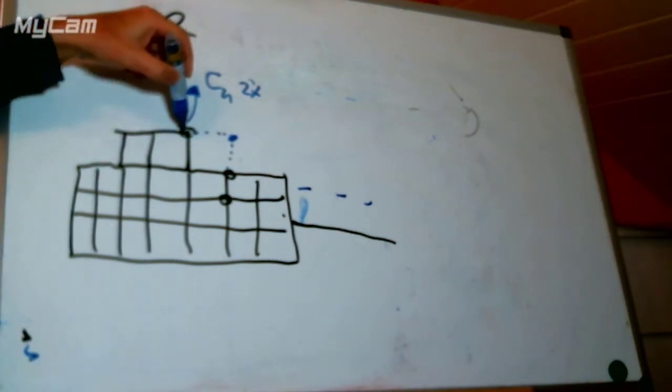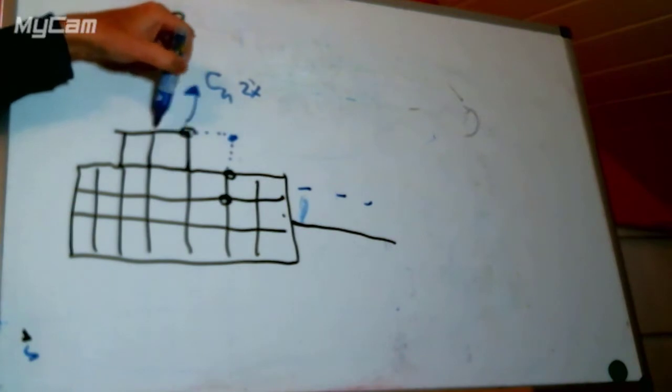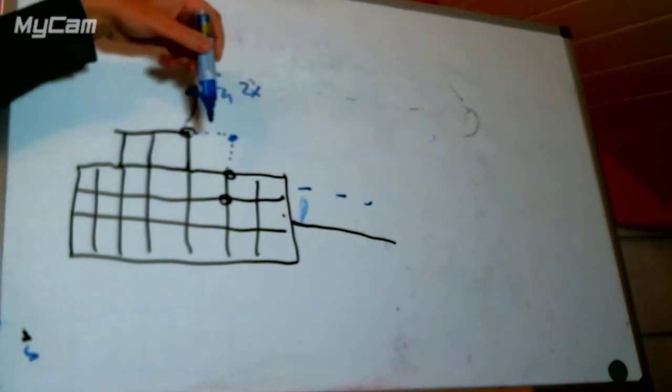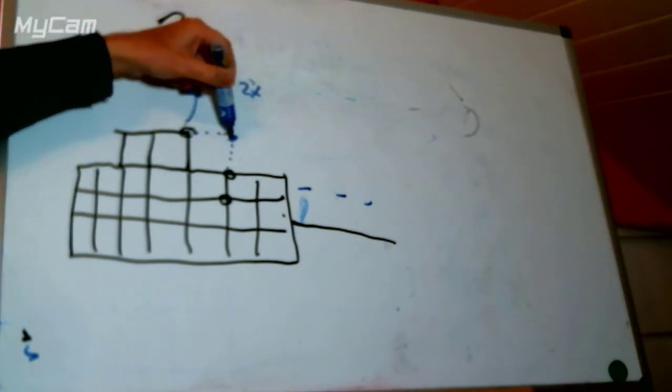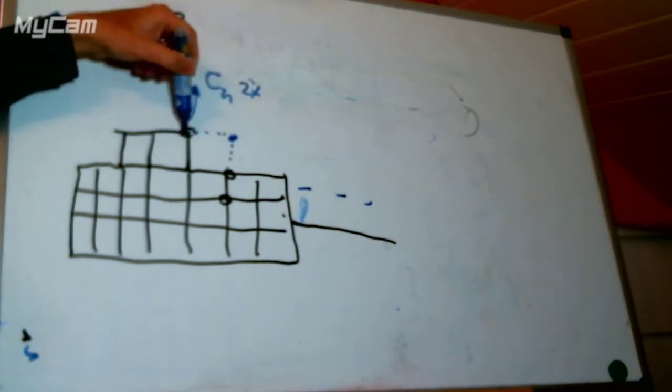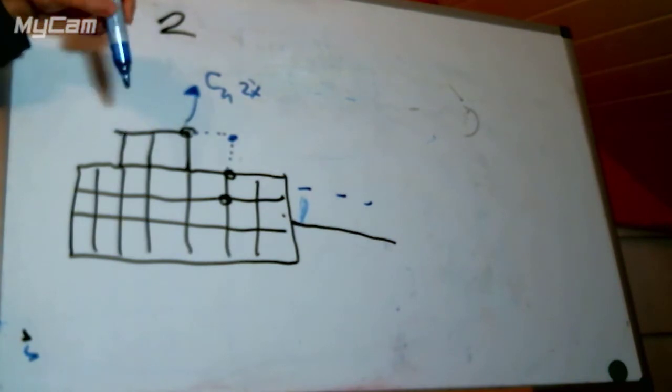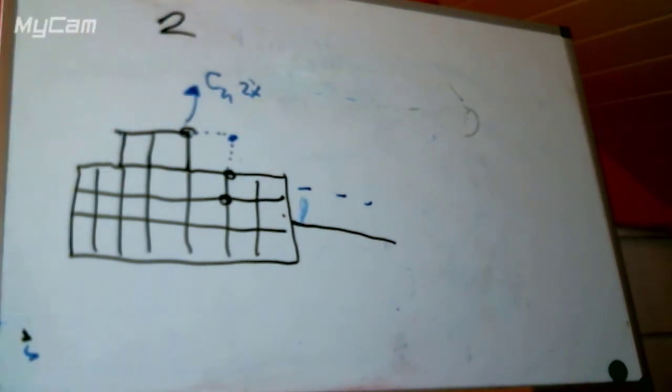So our steps can start to heal, and any copper that's forming out of solution will tend to go on here, and any copper that's being lost will tend to be lost from the corners, and we will tend to end up with slightly less steps, a slightly nicer surface than we had to start with. If we wait for infinity time, we can imagine thermodynamically that we possibly would end up with a single crystal, but we would have to wait for infinity time.